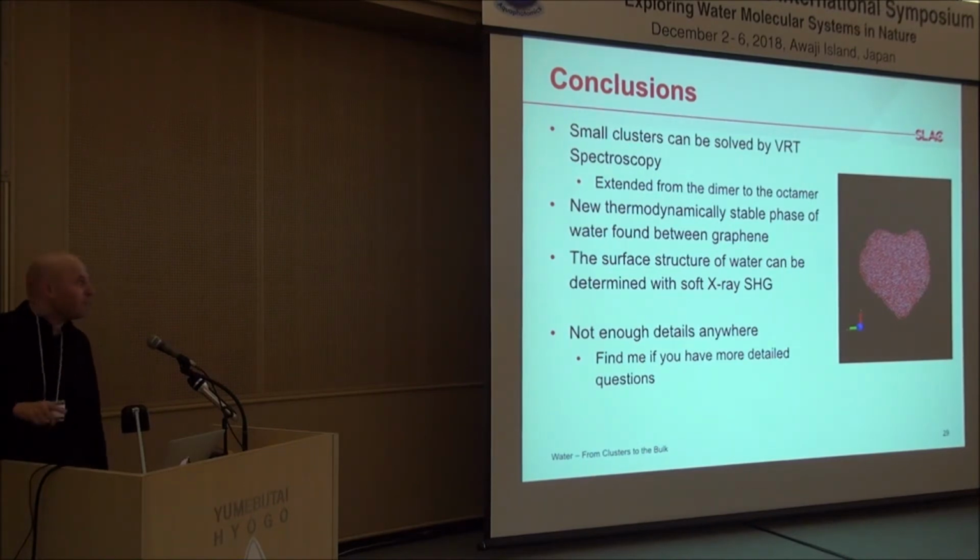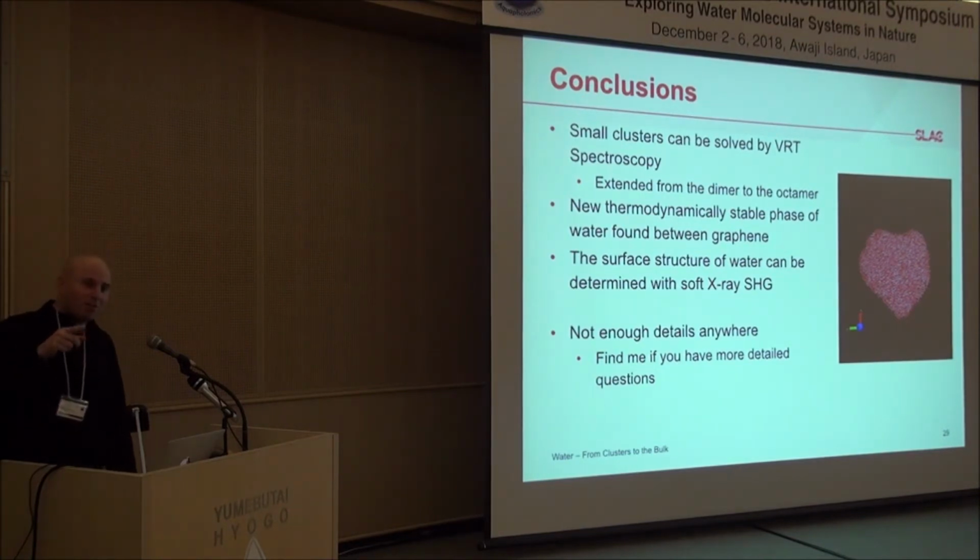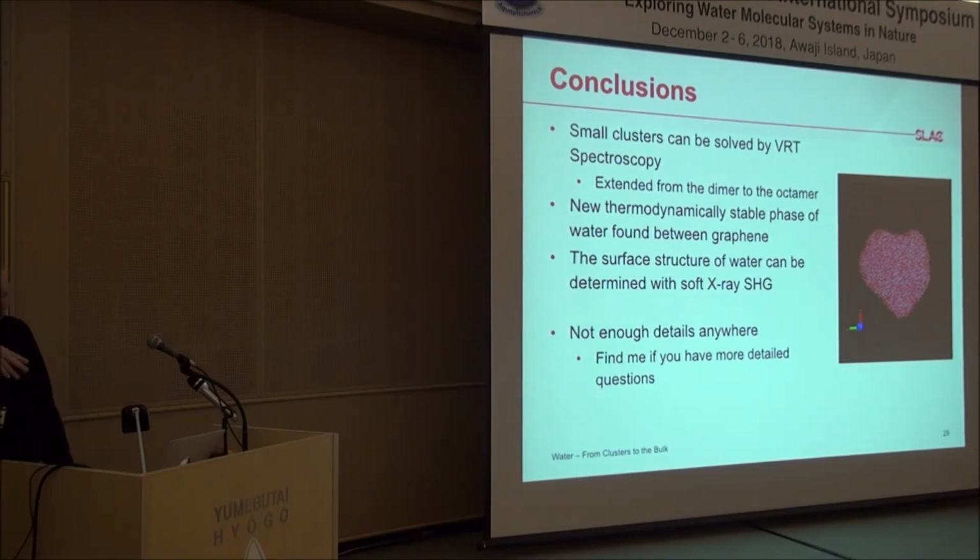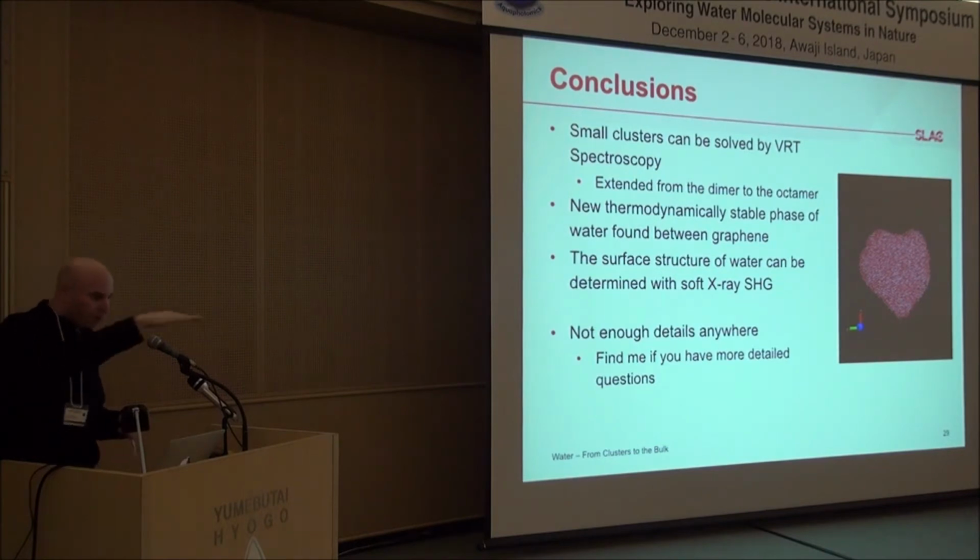And I forgot to mention this, and I'm going to mention it now. That phase of water, if you didn't trap it, diffuses about an order of magnitude faster than the solid and about 2 orders of magnitude slower than the liquid. So whether that's a solid or a liquid is left as an exercise to you. But it diffuses like a wave. The whole thing will move together.